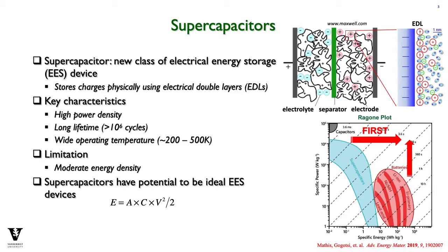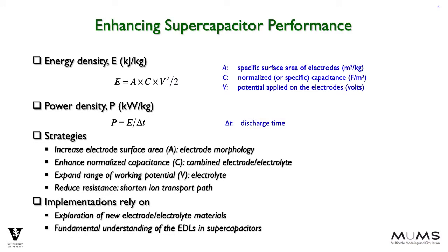Consider this equation for the energy stored in a supercapacitor. The energy density of a supercapacitor is given by the specific area of the electrode A multiplied by the specific capacitance C and the applied potential V. The maximum value that V can be is determined by the electrochemical stability limit of the electrolyte, i.e. the potential beyond which the electrolyte decomposes. The power density is the energy density divided by the charge discharge time, which for supercapacitors is of the order of 1 second.